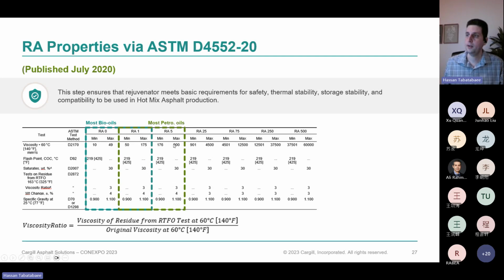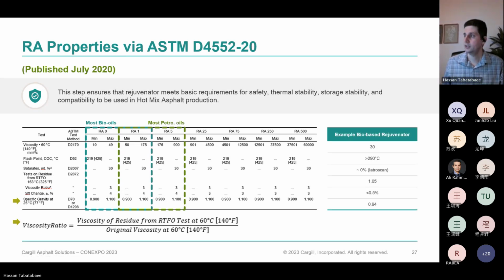Simply, it was an expansion of the table that now makes it apply to both bio and petroleum-based additives. Most petroleum-based additives used in bitumen are probably in RA1 or RA5, which is a slightly higher viscosity. You can see here an example of a bio-based rejuvenator with a viscosity of 30 at 60 C that will fall squarely in the middle of this RA0 category and can easily meet these criteria.